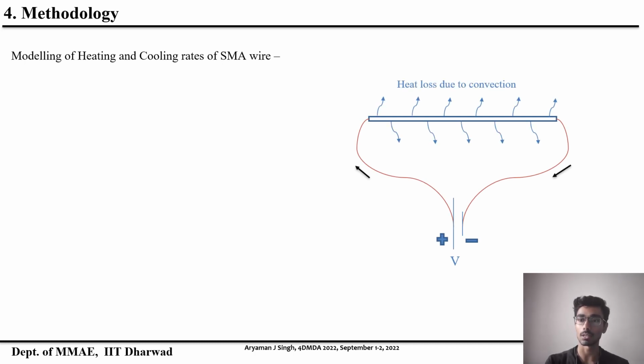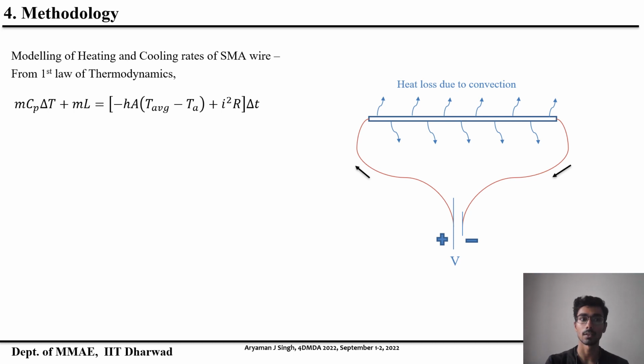Taking all of these into account, the heat transfer equation for the wire is derived from the first law of thermodynamics as follows. On the left hand side, the mC_p ΔT term is the net heat energy stored in the wire. The mL term is the heat energy lost due to latent heat of transformation of the shape memory material from martensite to austenite. On the right hand side, you can see the heat loss due to convection and heat generated due to Joule heating.